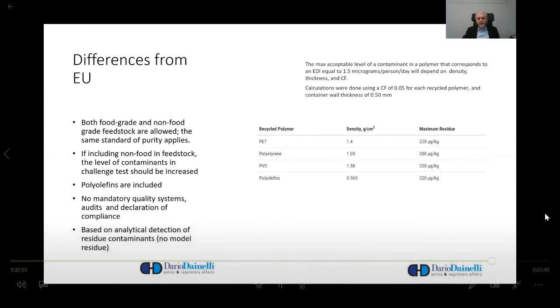That means that there's nothing such as residue contamination here. So you only have a maximum residue which can be calculated for different polymers. So you see a maximum residue on polyester corresponding to 220 micrograms per kilo, of polystyrene 300 micrograms per kilo, of polyolefins 320 micrograms per kilo, and of PVC. And in principle, you can make the same calculation for any type of polymer, which means that this system is much more easily applied to polymers different from polyester.